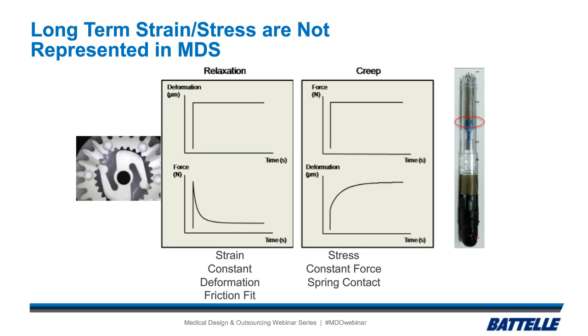So these are things that we can, again, test for with a DMA, but we need to do them using time-temperature superposition. Since we don't have years to wait to do the test, we can do the tests at higher temperatures and then relate those back to room temperature and longer time. So that's how we get it measuring long-term properties in a short amount of time using some standard equipment.